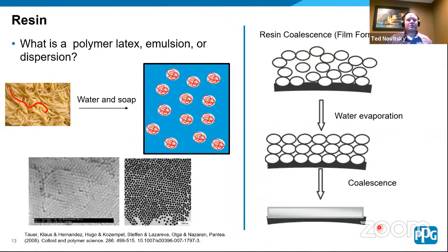So let's bring it back to paint. So if we have these polymers that are really good at keeping water out of the substrate, how are they in water in the first place, right? So what we do is there are a variety of processes here that we take these noodles, right? And we use water and soap to disperse them in water. And we'll get to the water and soap here in a second, because this is important. But we actually take the polymers and disperse them in water to make little particles of polymers that are floating around in water. And typically for architectural, they're anywhere from 50 to 200 nanometers, which is pretty small.